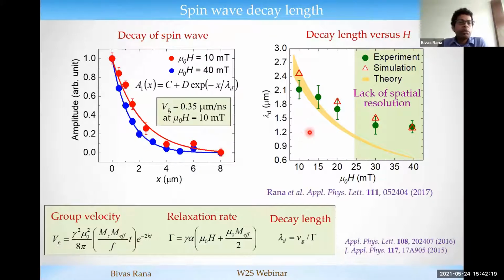So here are more characteristics of the spin wave excited by VCMA in this thin film. Basically, the most important point is the decay length, which we measured is roughly around 1 to 2 micrometers, but it decays as we increase the magnetic field. Because if you see the expression of the group velocity, as we increase the magnetic field, the frequency increases, so group velocity decreases, and the relaxation rate, which is also a function of magnetic field, also increases. So that means the decay length, which is given by this formula, should decrease as we increase the magnetic field.